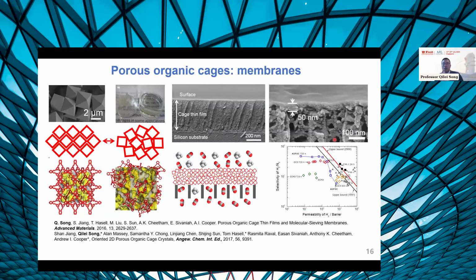Apart from the polymers and the MOFs, we also did some work on porous organic cages. This is work in collaboration with Professor Andy Cooper at Liverpool. We took some of the porous organic cages and fabricated them into thin films and membranes. We were able to get good performance at the beginning, but these porous organic cages suffer from physical aging. After a certain period, you can see that the gas permeance decreased.